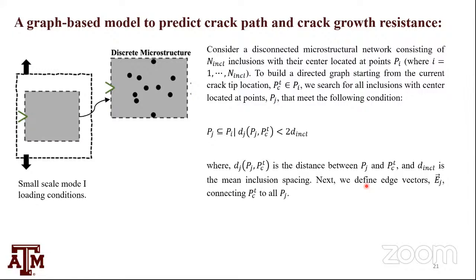How we're going to build the graph in this case is just by relying on the things that we have learned so far. We know that two times the mean inclusion spacing is what dictates the fracture toughness, from the 3D calculation that I did, which we published in 2014, from work done by Rice and Johnson decades before that, which showed that between two voids, two times the mean void spacing tends to dictate the critical crack tip opening distance. So, okay, let's focus on a small piece of the microstructure at a time. I'm only going to focus on a region that is within two times the mean inclusion spacing. Now I have certain inclusions, and I'm going to connect all these inclusions with direct straight lines from my crack tip. So I'm going to simply draw these vectors connecting my source to all these points.